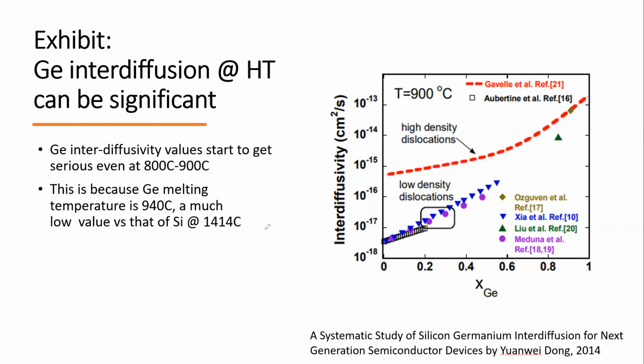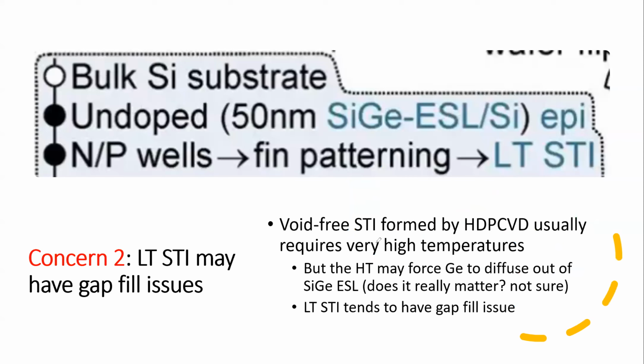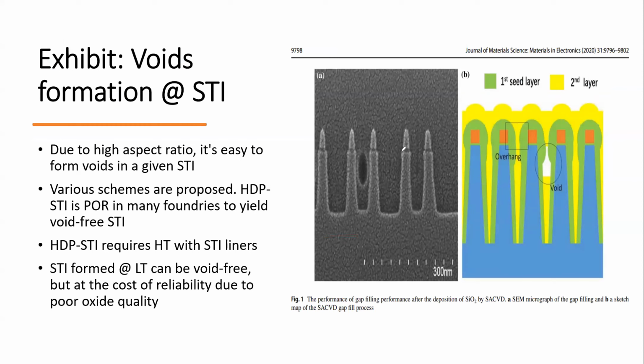You need to lower the temperature. You cannot have too high a temperature, and that's the reason you said low T. But at low T, you bump into the problem that you need void-free STI. The void-free STI is difficult because STI right now has a very high aspect ratio. This aspect ratio is just a simple one; the current one is even higher. The aspect ratio is so high, and you want a complete void-free process to fill it nicely. Sometimes you cannot, you see.